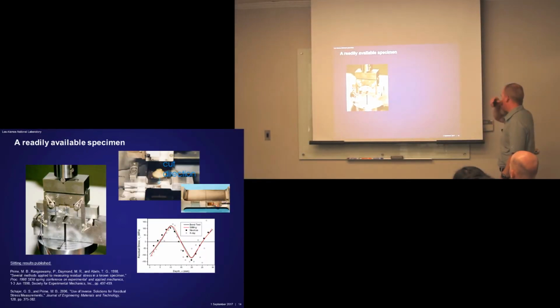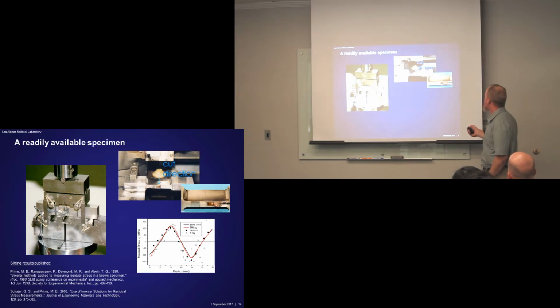All right, so just cut it in half. I had a specimen readily available, so we had been making these plastically bent beams to make a known stress specimen for the slitting method, and had published that. Here's the slitting test. We cut by EDM, same thing you guys do. There's the strain gauge. This is after the cut. There was a strain gauge on the top surface as well. And we had published all that. And there's the black line, which is the prediction from the bend test.